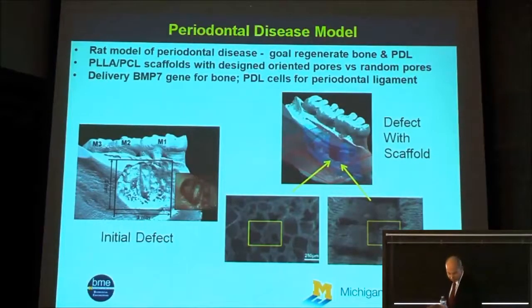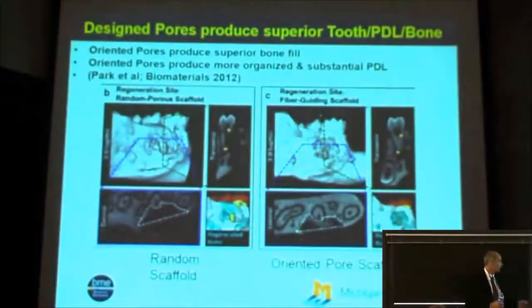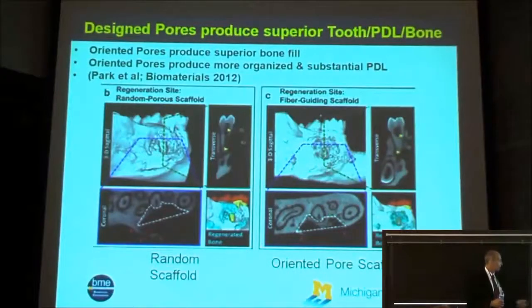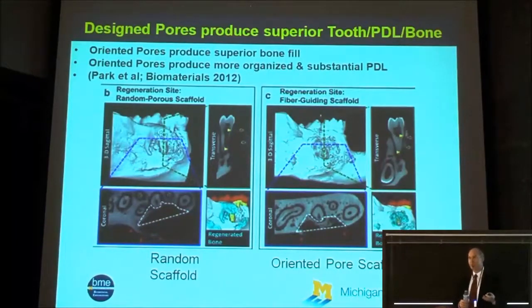And we wanted to see, again, does it make a difference? And the answer is yes. You can see that in terms of the bone regeneration around the tooth root, this is the random scaffold, and this is the oriented pore scaffold. And we know that in looking at this, having the oriented pore scaffold gives us significantly greater bone growth around the tooth root, as well as, I don't show the data here, but more oriented ligament fibers that grow up to the cementum.